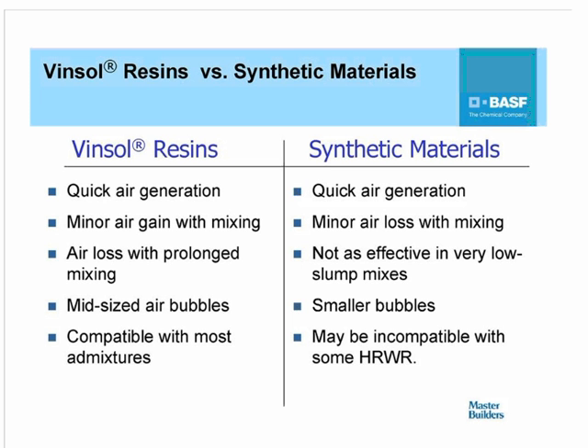These materials, again, the synthetic materials, will have minor air loss with mixing. They generally form much smaller, very stable air bubbles when used in concrete. And they may be somewhat incompatible with some high-range water-reducing admixtures, depending on the particular chemistry. But both of these chemistries, either the vinsol resins or the synthetic materials, are very, very effective in producing concrete that has very good freeze-thaw resistance.